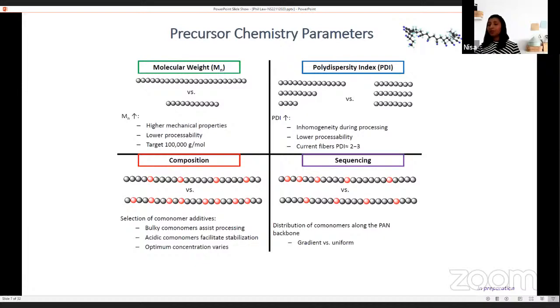About 90% of carbon fiber production is from polyacrylonitrile, or PAN, and this PAN will have 2 to 10 weight percentage of co-monomer content in it. The choice of the PAN co-monomer polymer matters. It has to have a certain molecular weight between 100,000 to 200,000 with a polydispersity index of 2 to 3. And again, the composition, the sequence of the co-monomers in this PAN chain, also matters.